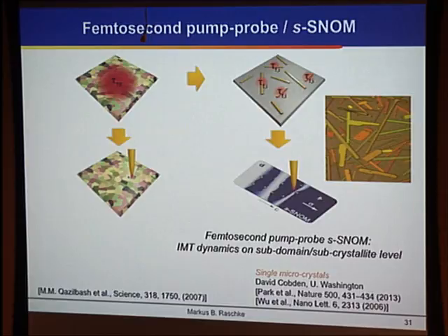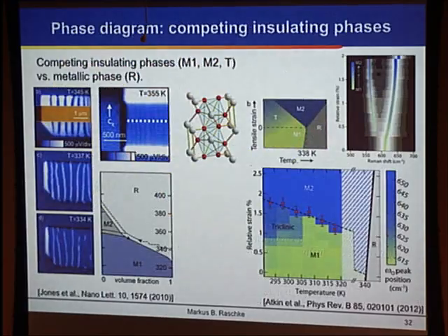And then what I'll show you is where we are driving this, really towards being able to do ultrafast spectroscopy, driving the system far out of equilibrium on a local scale, really on the level where the defects control the domain behavior, as well as where the strain also defines what type of phase the system is in initially, and then what the final states are.